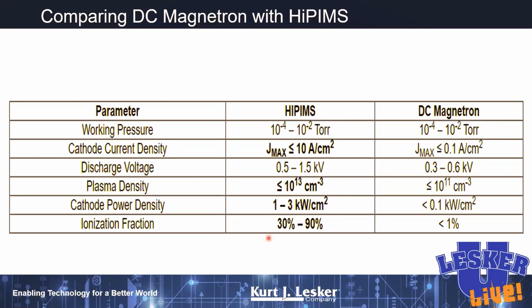And look at this ionization fraction. In some cases, and I'll show you some images on titanium, we're going to get an ionization fraction, a density of ions in the plasma itself, up close to 90%, whereas with DC magnetron sputtering, we rarely see something more than about 1%.